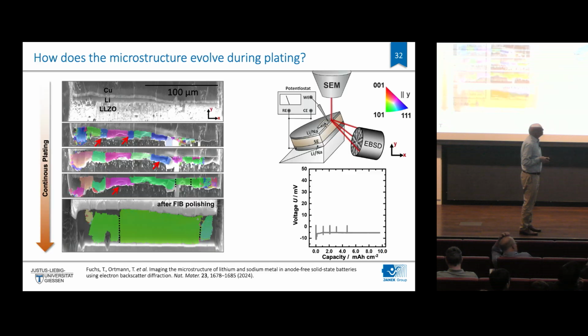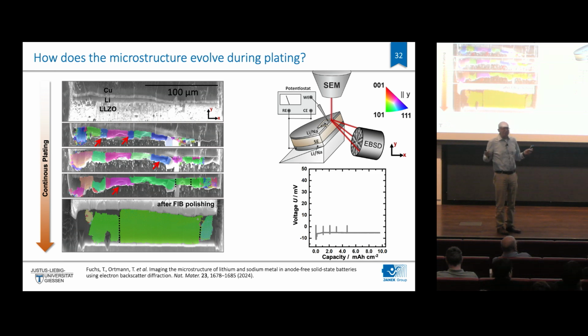So what governs the microstructure during plating? We looked a bit deeper into that, and I will make that short. At the end, we found that, in fact, the thickness is a major decisive factor for the microstructure of the film. And the reason is grain growth is so fast that, in principle, the grain size always adapts to the film thickness. It's a competition between the interface energy and the grain boundary energy. If you have a thin film, the interface with the current collector and with the electrolyte determines the energy of the film. If it grows thicker, you have more and more relative grain boundary area, and then the grain boundary energy determines the size.